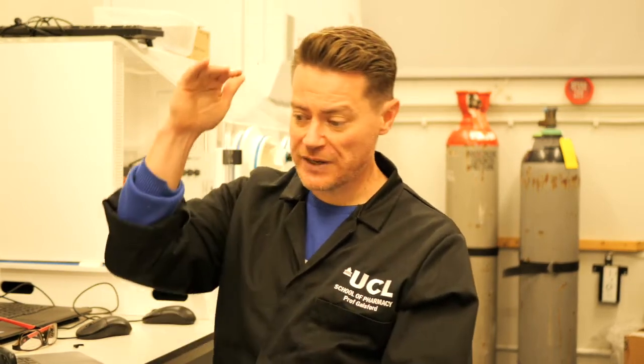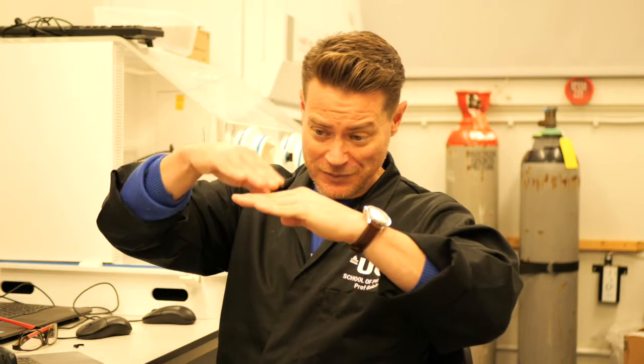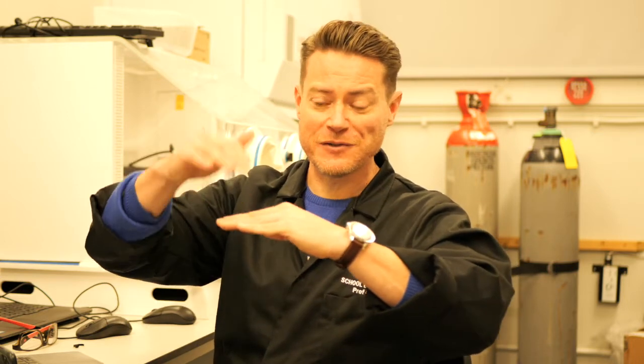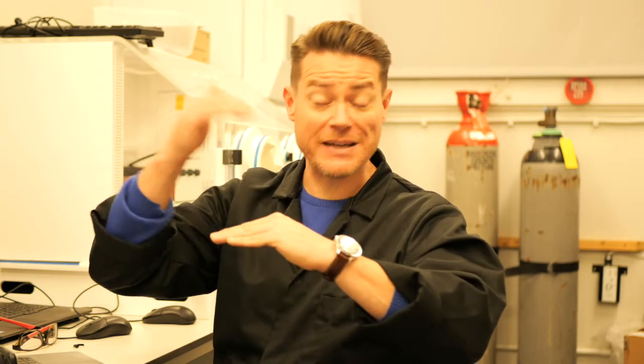So the way this works is the tip itself is made of metal, and because it's metal you can pass an electrical current through it. Okay, so if you pass a current through it, you can measure the resistance of the tip. If you bring that tip down onto the surface of a material, if that material is not conductive in any way, you can pass current through the tip, nothing will change. But if that material was, say, a metal or something that was conductive, and you bring the tip down, some of the current that you pass through the tip is now being taken away by the material. And so the amount of current that you've got to put through your tip to maintain it changes. And so by measuring how much current you're putting through the tip, you can tell something about the thermal conductivity of the material on which the tip is resting.